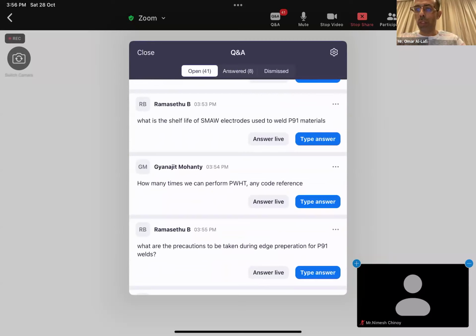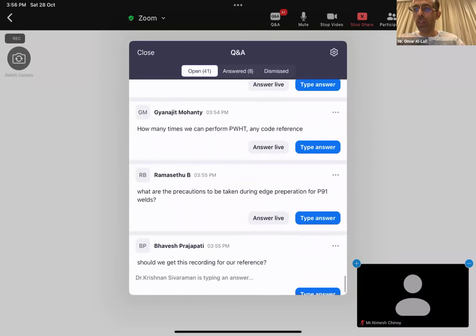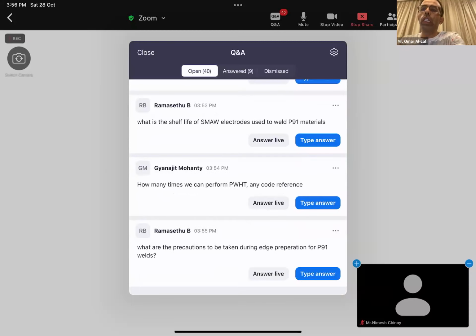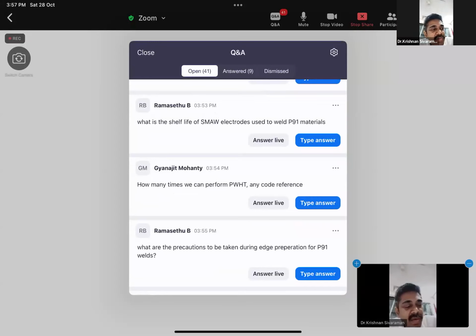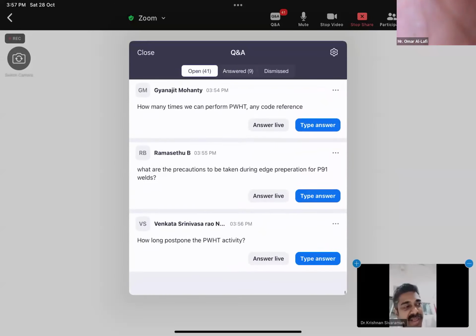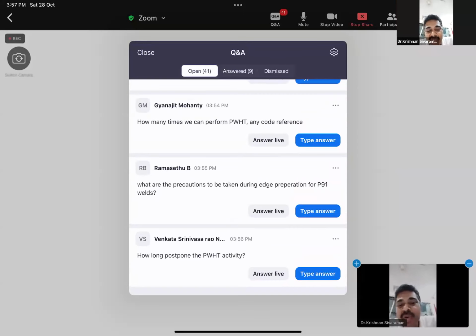How many times can we perform PWHT? Any code reference? In the PWHT, I don't see any problem if we do it 2 or 3 times, but I don't know any reference that suggests a maximum number of heat treatments for P91 or other material. Generally, these are done for 3 cycles. One during fabrication, one maybe for any repair in fabrication, and one for the customer for future repair. So generally 3 cycles, and base material and also the weld consumable are tested for these 3 cycles. Yes, that is the general practice. This is the practice, but is there any code reference for specifying a maximum number of cycles? No, the code is silent on that.